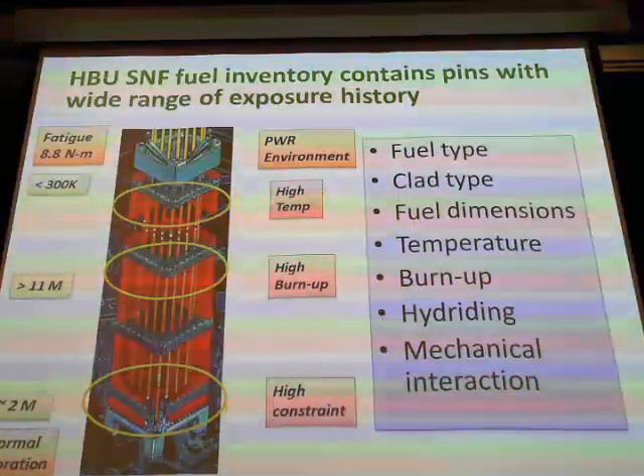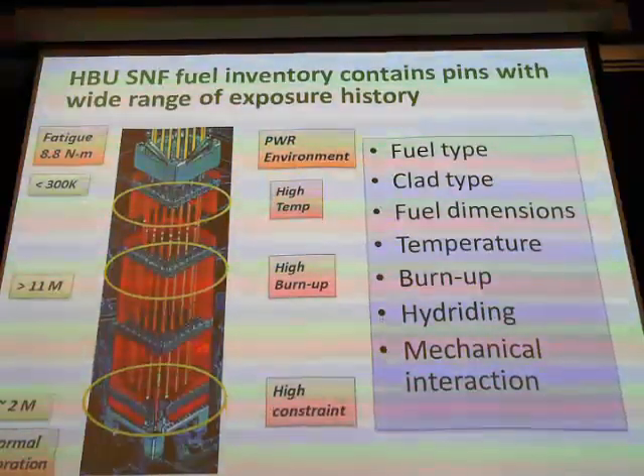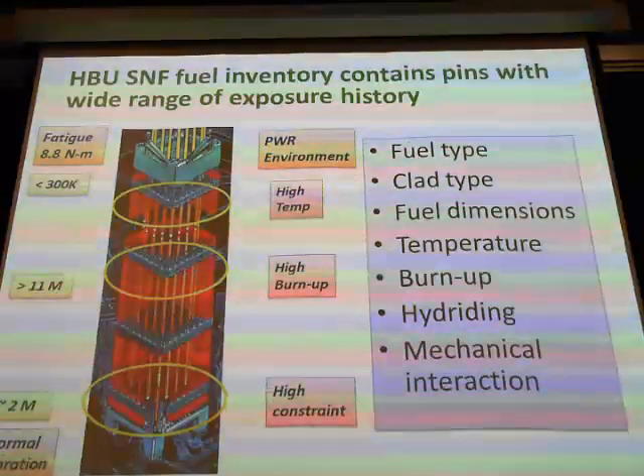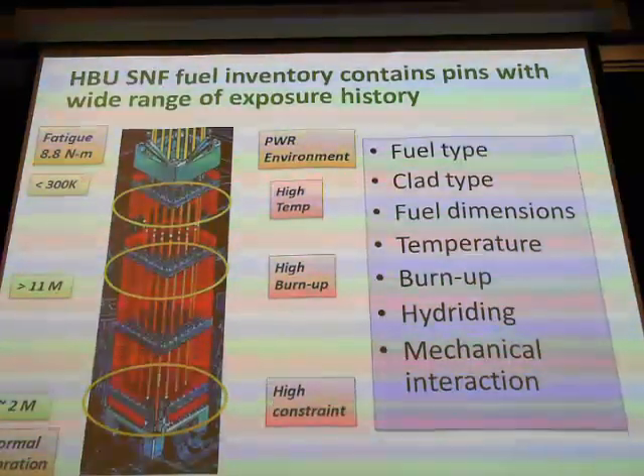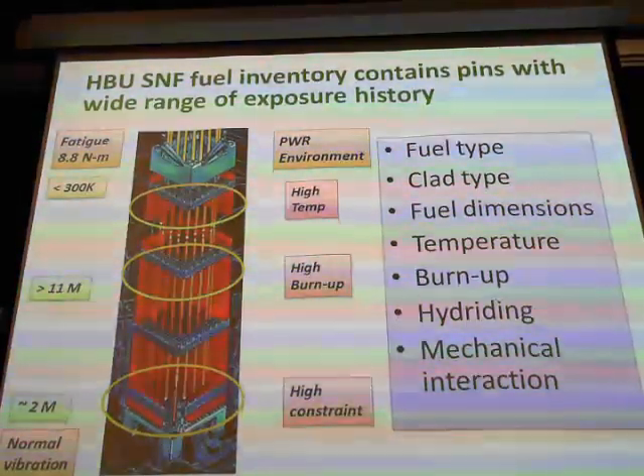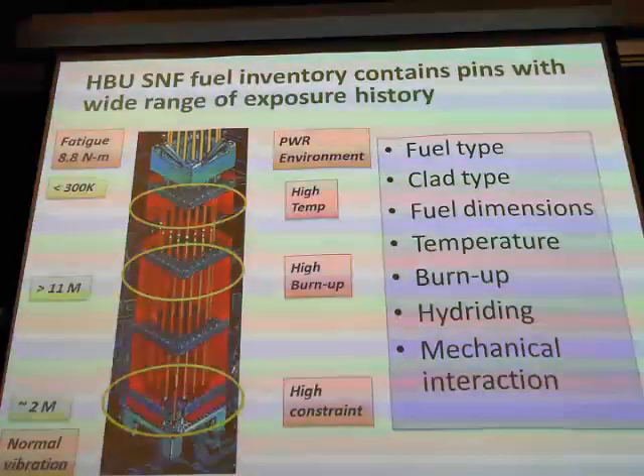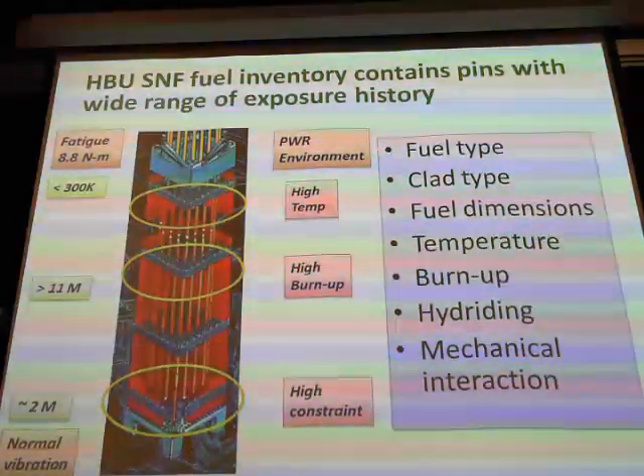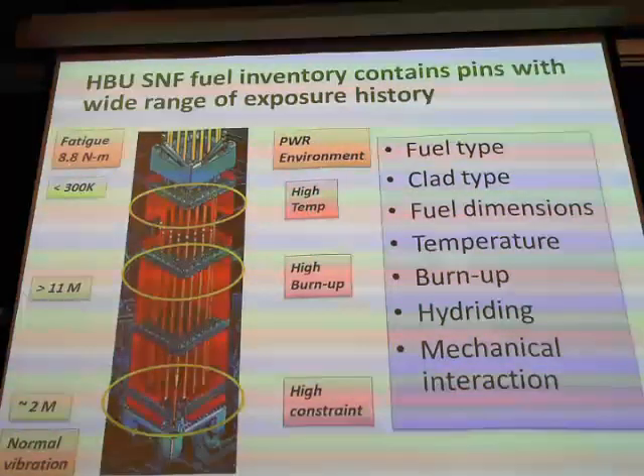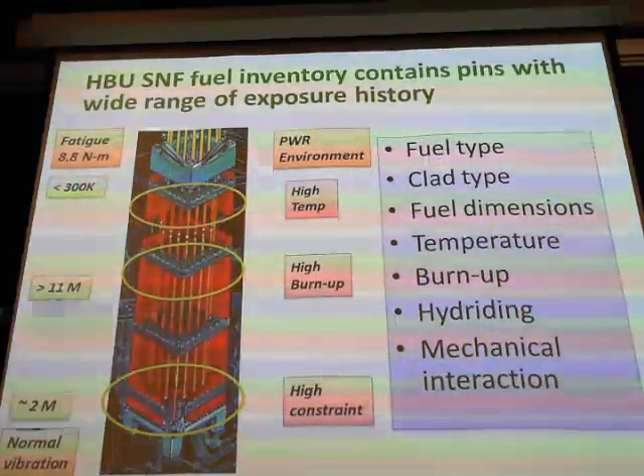Okay, this will give you some example. Even under one single fuel rod, depending on where you take your sample, the response is very different. For example, on the top level, basically higher temperature. This picture I'm here limiting myself to the PWR environment. Depending on fuel type, cladding type, fuel dimension, and the pellet length, we find the pellet length has a lot to do with the damage mechanism. And burn-up level, hydriding, mechanical interaction, such as here, both ends, especially the bottom one, have very high constraint. So in the middle one, we call it a high burn-up level, I tested at 8.8 newton meters target loading, and it survived even after greater than 11 million cycles.